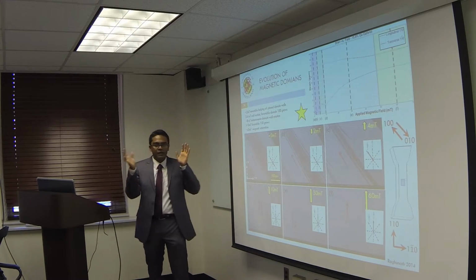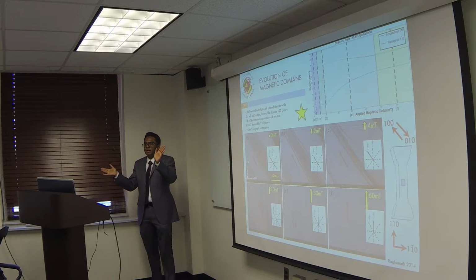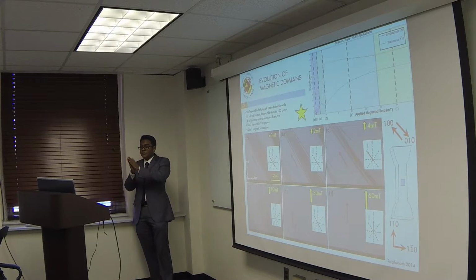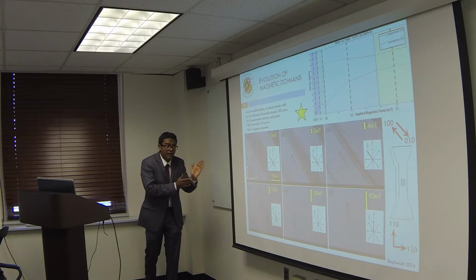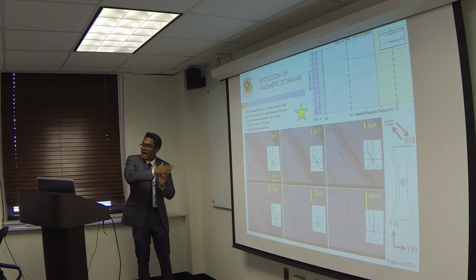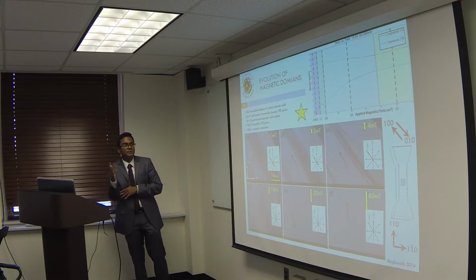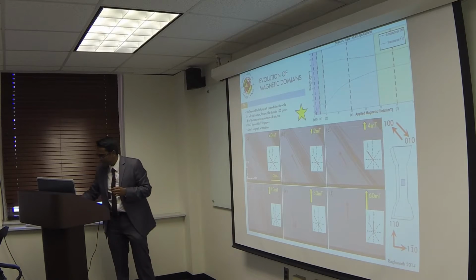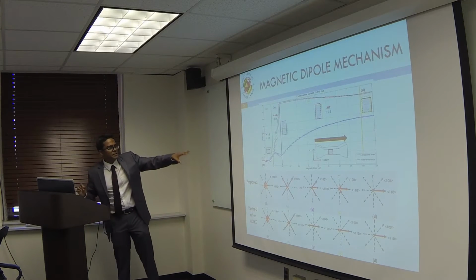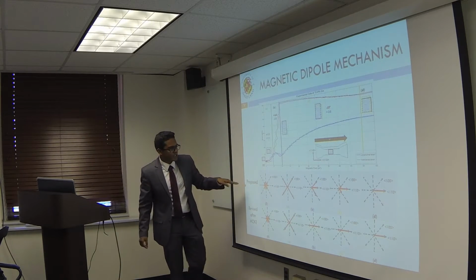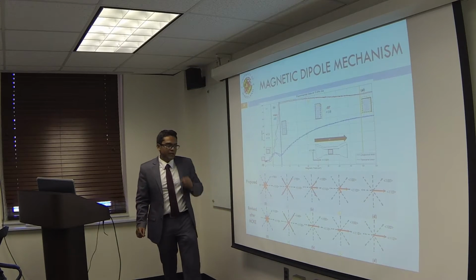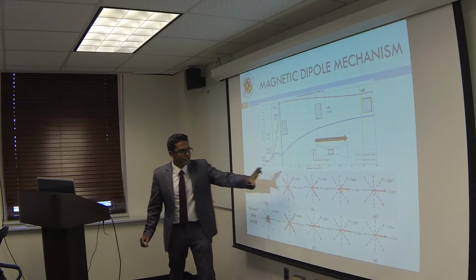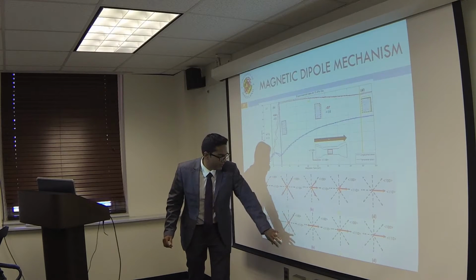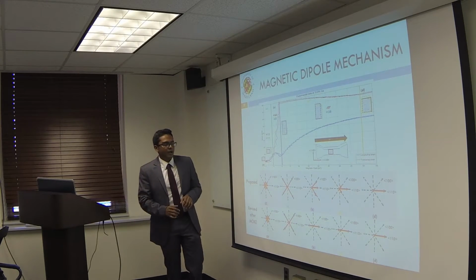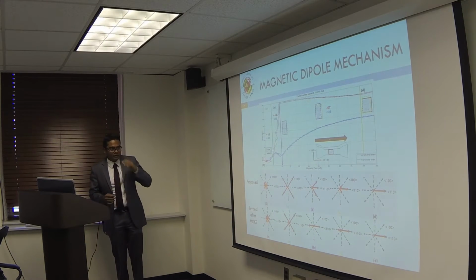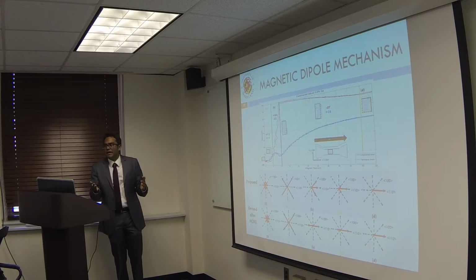Instead of having it go along the 100 directions and the 110 directions, we had it go along the 100 directions alone, and then flip over completely to orient themselves along the 110 direction. So this makes it easier for me to explain this. So this is the proposed mechanism, and it turns out that there's something going on between stages A and B and C as well that wasn't expected.